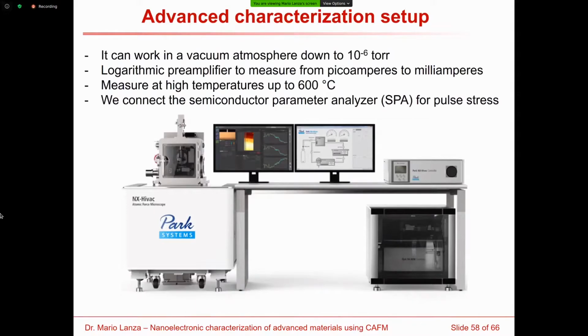And the study that I'm gonna show right now is done with one advanced conductive AFM. It is a very new tool that we have acquired in our lab. It is the NX-HiVac from Park Systems. This conductive AFM is unique because it allows you to perform four different tasks simultaneously, which is measure in a vacuum chamber, measure with a logarithmic amplifier, measure at high temperatures, connect a semiconductor parameter analyzer, and also we can measure the current in tapping mode, which is very important to avoid lateral friction. So this is the only AFM in the world that can do this.